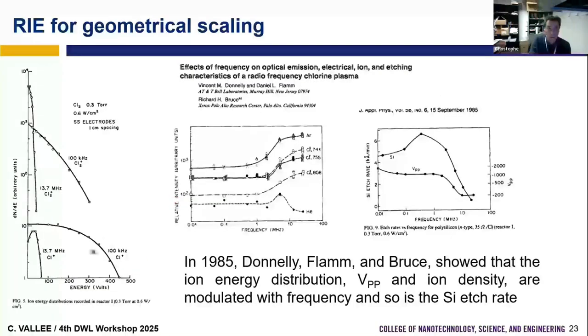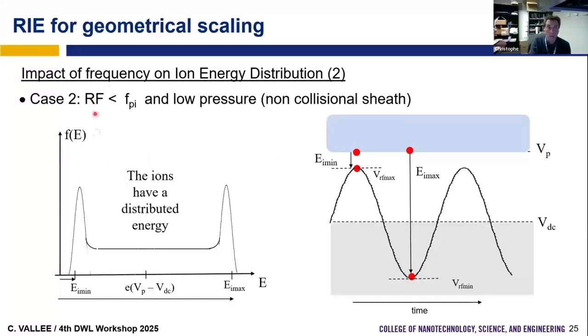And now if I go back to the case where we apply a low frequency generator, this frequency, for example hundreds of kilohertz, is lower than the ion plasma frequency. What does it mean? It means that now the transit time for the ion to transit the sheath is very fast compared to the time of the oscillation. So now the ions will take, as they transit, the instantaneous value of the RF voltage, and not the VDC.